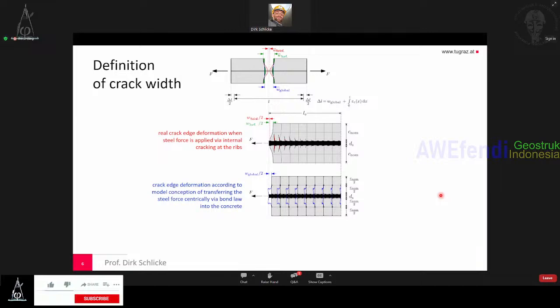What we do now in calculation is not calculating these internal cracks. We simplified all of this, the weakening due to internal cracking, by a sort of a spring, so a force-deformation relation. And we assume here uncracked concrete. So the internal cracking is represented by a weak spring, and the external, or the primary crack, is represented as a primary crack, which has of course no deformation over the height of the concrete cover, since we apply the spring from the reinforcement to the center of gravity of the concrete cover.